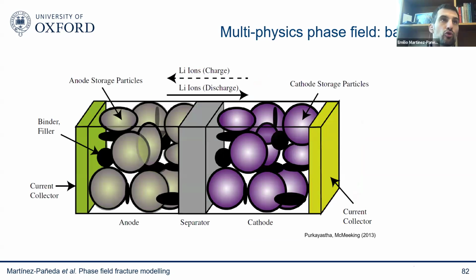And what happens is that every time you charge and discharge your battery, these lithium ions are embedded into these anode and cathode particles. So these are typically ceramic materials, and you get this lithiation process where these lithium ions accumulate in these particles here, and then when you charge your battery, they leave from here and go the other way, and electrons go the other way around.